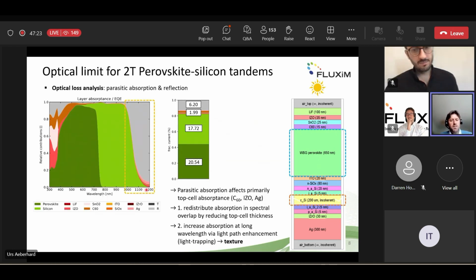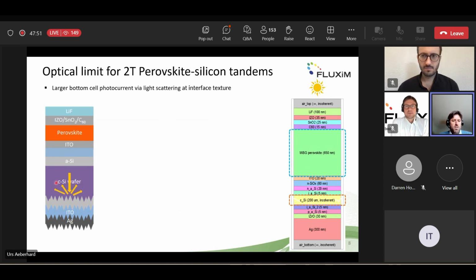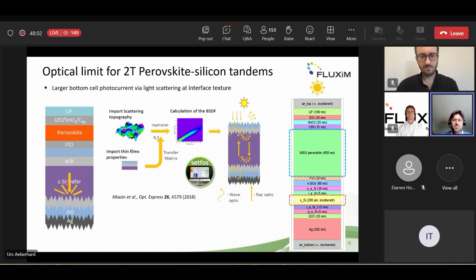So therefore, we now look at this part where we have significant loss due to reflection. And we have seen in the previous talk also that one way of reducing these losses is to increase the light path length in the silicon via scattering at the texture. So first, we consider a situation where we have just one interface that is textured, which is the rear interface here. So the incident light scatters into larger angle and the light path in the silicon then is increased.